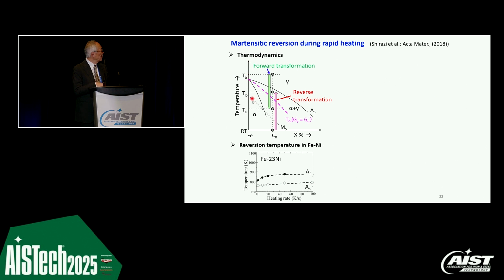Here's the phase diagram with the austenite and ferrite, and this is the two-phase field. This is the cooling down, and of course we have the driving force for the forward transformations. And there is the case of the reverse transformation like this. And these are the characteristic lines for T0, where austenite and ferrite have the same energy. So below that, for forward transformation, we have the driving force for the martensite transformation. Above that, we can also have martensitic reversion, although we have more diffusion occurring at high temperature.